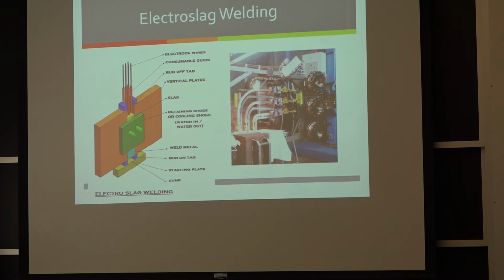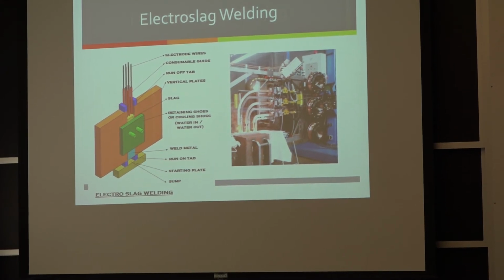But that's why I was paying $100 a pound. I was crushing up old pieces of optical crystals to make a flux that was just going to melt. But the Soviets would take commercial purity calcium fluoride and strontium fluoride and other things, and melt them in a platinum furnace under a hydrogen fluoride atmosphere to get rid of the oxygen, the calcium oxide. 1% calcium oxide impurity in your flux would destroy the mechanical properties of the weld in terms of oxygen and stuff. So very, very critical on the purity of the flux.